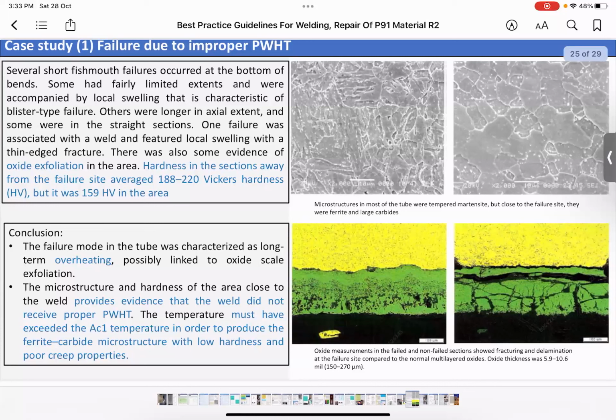So the conclusion is the tubes failure was characterized as long-term overheating, possibly linked to oxide scale exfoliation, and the microstructure and hardness of the area close to the weld provide evidence that the weld did not receive proper PWHT.